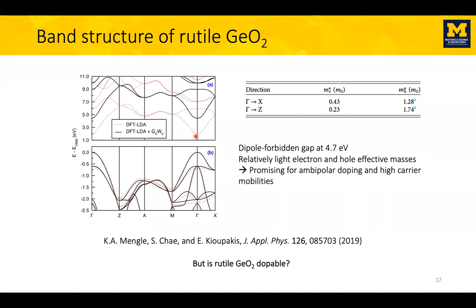But the most important property here is the effective masses. And what we found is that they are not too large. The electrons have a typical effective mass around 0.2 to 0.4 times the mass of the electron in empty space, and the hole masses are around one. So they're actually not too bad. Which is promising, that it should conduct not only electrons very efficiently, but also holes. It doesn't give us these flat bands we saw earlier in gallium oxide.